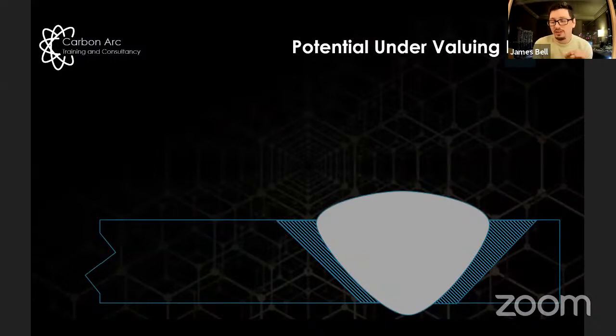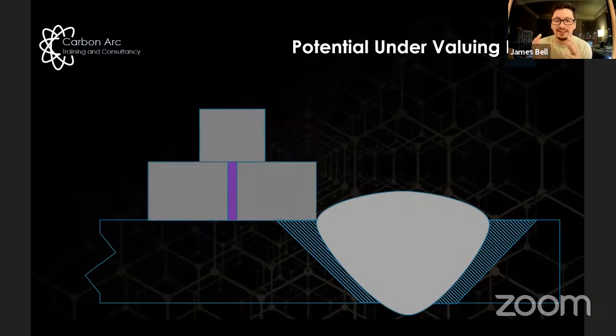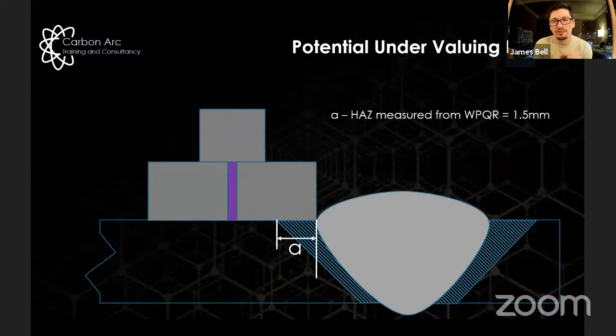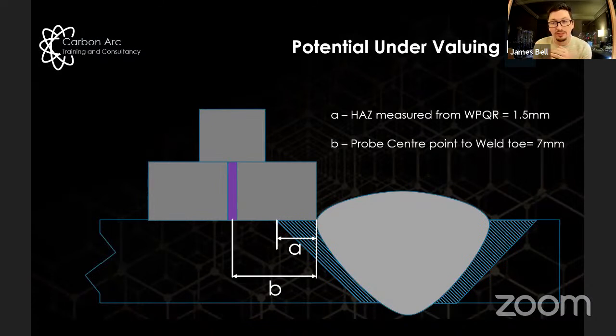What we also found was when we look at the heat affected zones that we were testing, when we bring the probe onto our weld, our heat affected zones measured from our PQRs were no bigger than 1.5 millimeters wide. The probe location at best was 7 millimeters away from that. So most of our probe was actually sitting in parent material, and we were never testing heat affected zones. Something else, just saying, like, is this process really what we want to do?